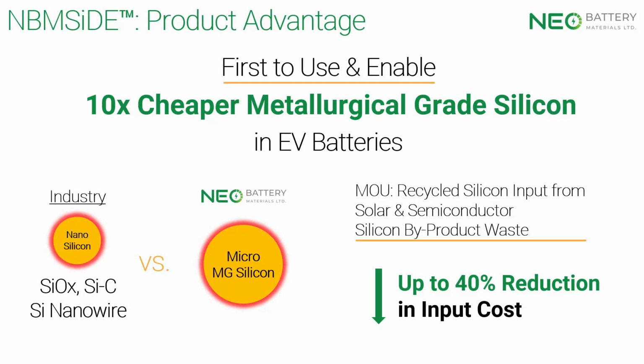As you might be aware, we just announced a deal with a recycled silicon player. That is why I was so happy to find this recycled silicon player, because they hinted they could provide pure silicon with high grade down to $15 or $14 per kilo, possibly, which means we could save an additional 30 to 40% reduction in purchasing cost, which will create significant price competitiveness compared to existing competitors.